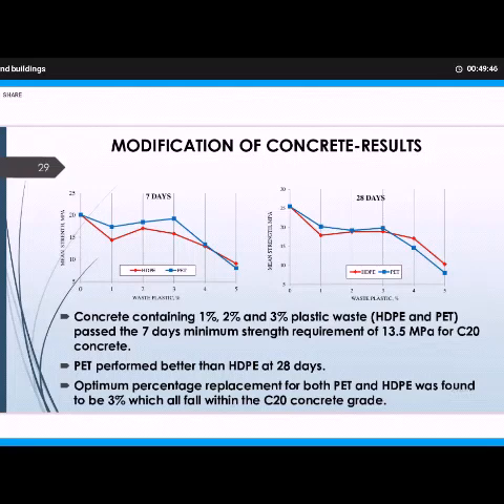So when you look at a 7 days compressive strength test, it is observed that PET and HDPE all reduce in strength as you add the plastic waste from 1% through to 5%. Compressive strength reduces as you add it along. But then it must be stated that the 7-day compressive strength was, however, within the required standard. Now we are looking at C20 as the grade of concrete, and the minimum strength requirement for 7 days when you are considering C20 grade concrete is 13.5.